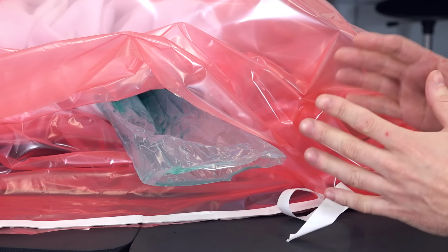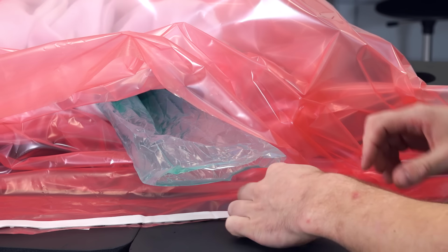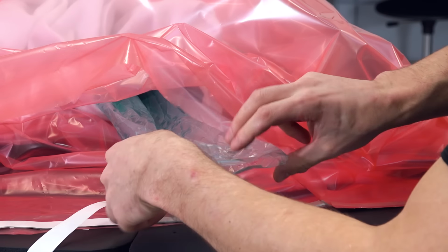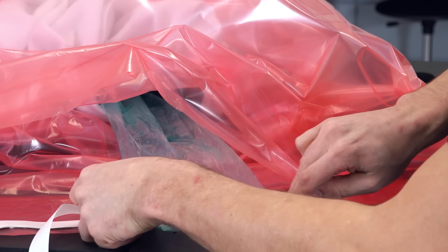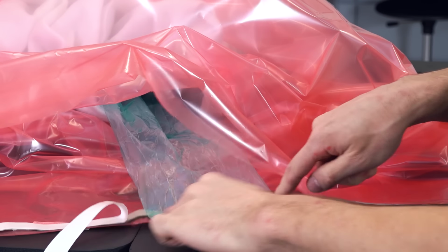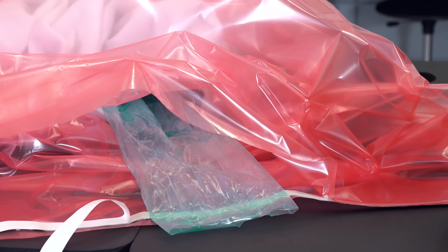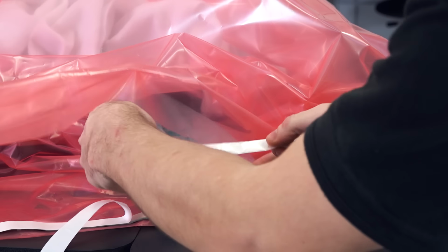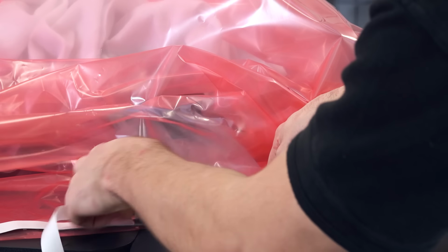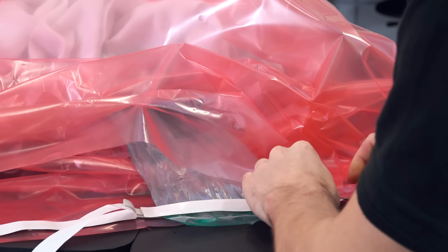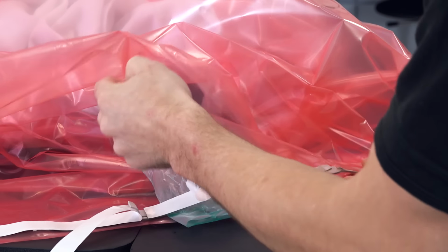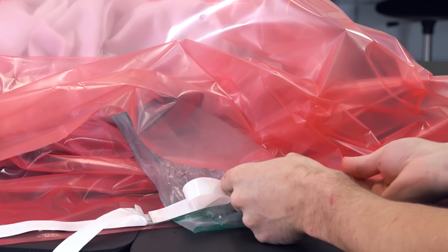So essentially, all we're trying to do with the inner bag is breach the seal of the outer bag. So we've got the seal to the outer bag, the pink bag here. So we draw the seal back, tack the inner bag across the sealant tape, then seal over the top of that bag with another section of tape, which then allows the outer bag to fully seal around it.